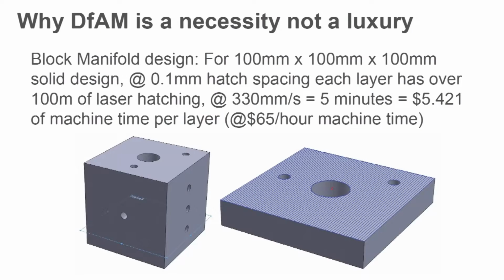Let's say you've got a 0.1 millimeter hatch pattern. That's a spacing between the laser beams. They vary between just under 0.1 of a millimeter to about 0.15 millimeters. For one 10 by 10 square, you've got about 100 meters the laser has to cover. If your laser is traveling at 330 millimeters per second, for a 100-watt laser, that's about right. If you have a 400-watt laser, you might be going at 1.5 to 2 meters per second.